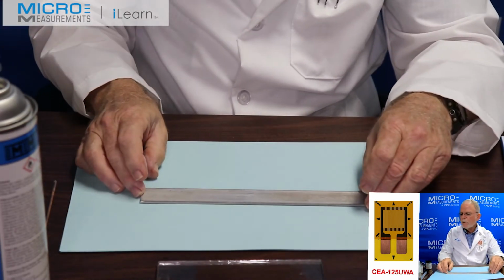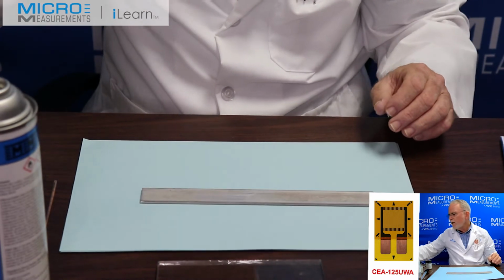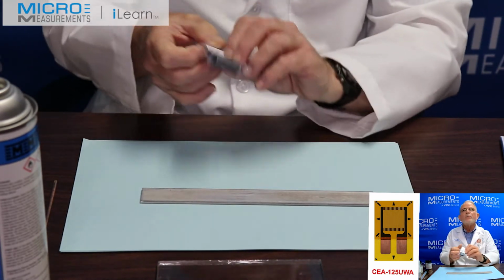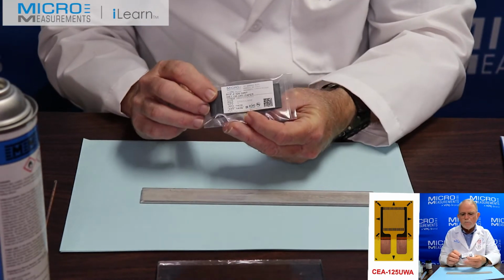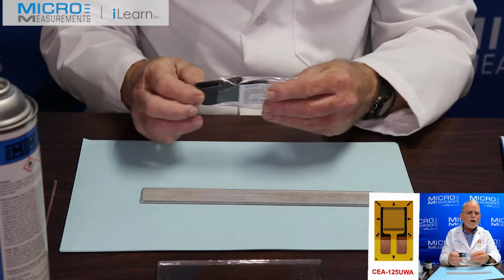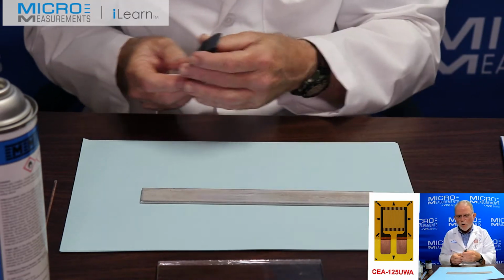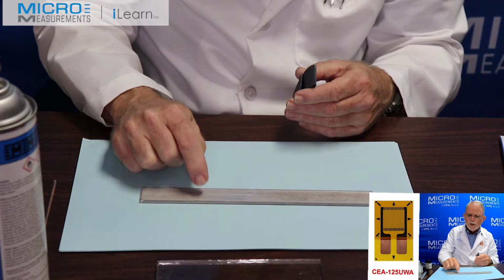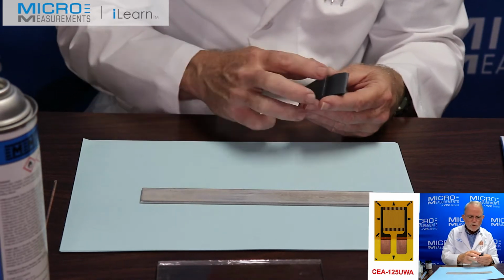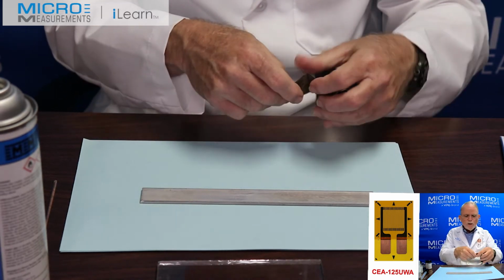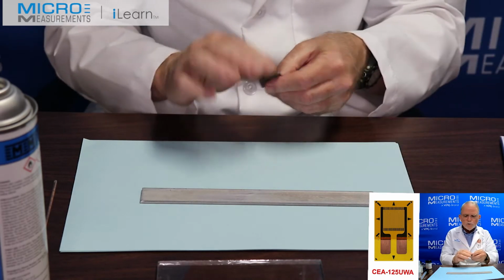So now I've degreased it. The next step will be to take our 320 grit, the SCP-2 silicon carbide abrasive paper, and I'm going to dry abrade the surface of the part. Now my strain gauge is going to be located right here at this alignment place here, so I'm going to abrade the area there and about an inch on either side of it.